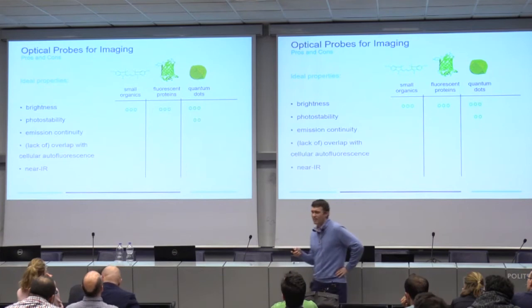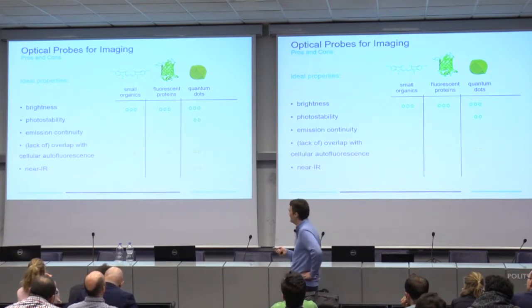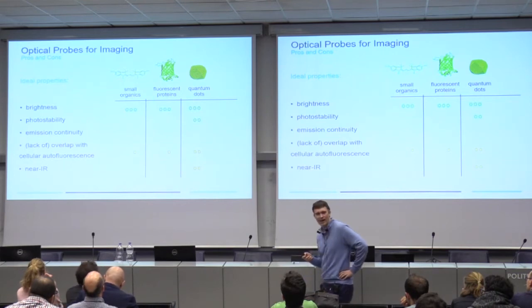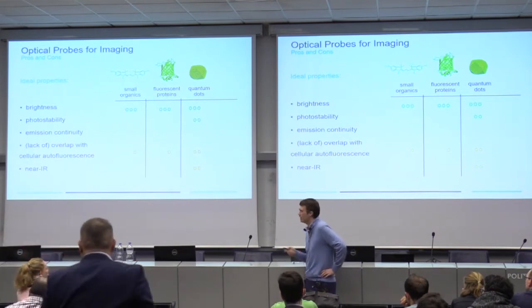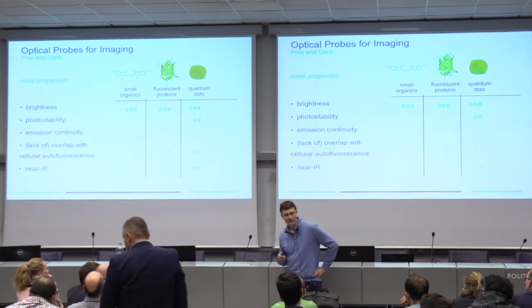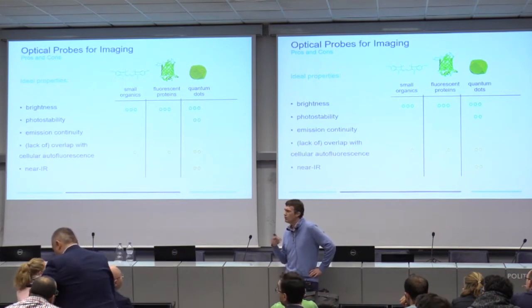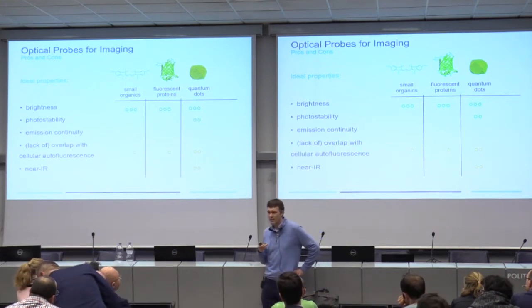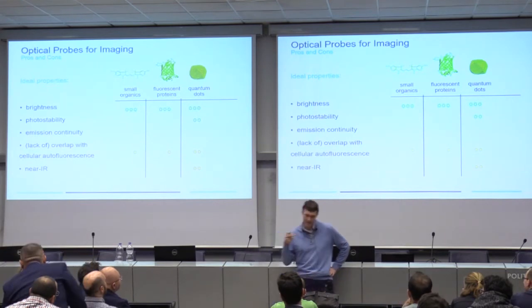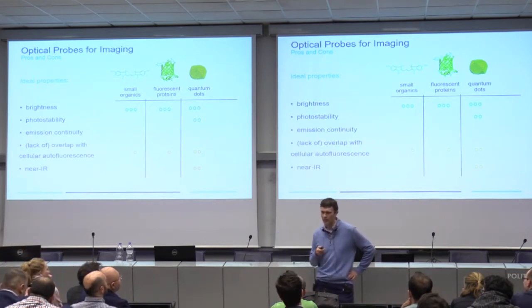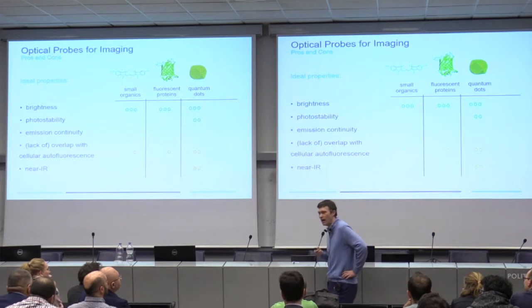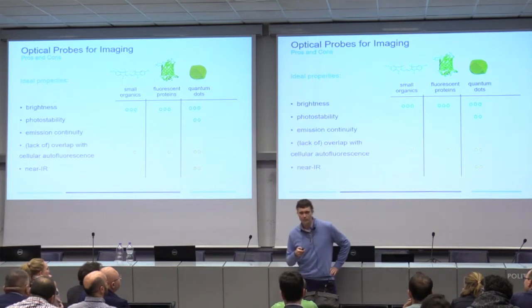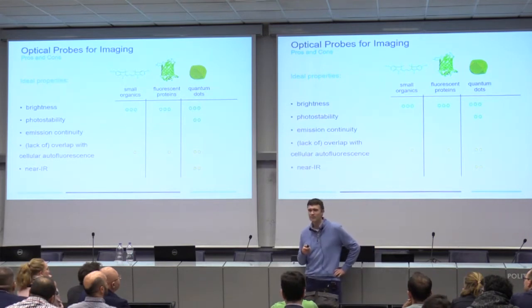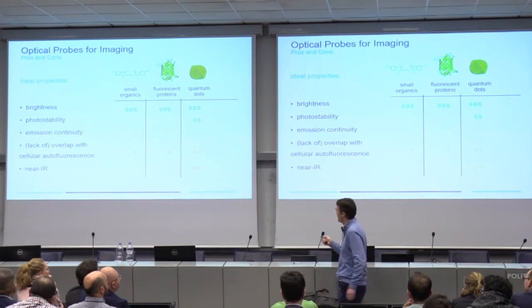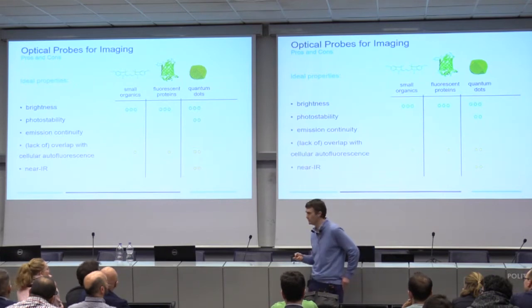But beyond that, they're generally bad. They're generally terrible at almost everything. So they're not photostable. So what does that mean? That means, especially for the organic materials, you can usually get roughly 1 million photons out of them before they die. They photobleach. There's some kind of irreversible chemistry that happens that gets rid of them. People will tell you that quantum dots don't photobleach, and they're lying to you. You can always make quantum dots photobleach, although they are more photostable, absolutely.